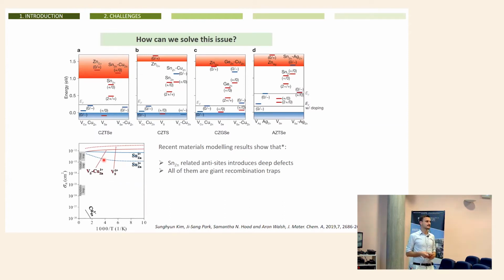After several years of discussion, because of course we know that we have a VOC deficit, this VOC deficit was identified as really related to the non-radiative recombination. The material used to exhibit quite low photoluminescence, indicating that we have quite a lot of non-radiative recombination. And after several years of research and also theoretical research, we found that most probably all the tin-related defects are at the origin of this non-radiative recombination and this VOC problem of the material. Currently, we believe that tin on zinc is the main problem, and we should find ways, strategies to try to avoid this defect that is quite complex to avoid.